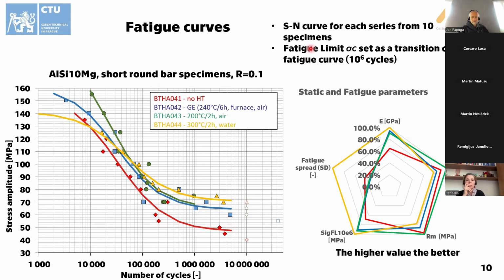I think it's not necessary to explain it, but we were using the end condition for the testing set to be a 10% decrease or drop of frequency and half a kilonewton difference in the amplitude of load, and the run-out condition was set to 10 million cycles. Now, what I would like to mention here is that the tensile properties well transcribed to the fatigue life properties, as you can see here, because the induced ductility of the T200 shows higher fatigue life in the high cycle fatigue region, and the transition to the fatigue limit.